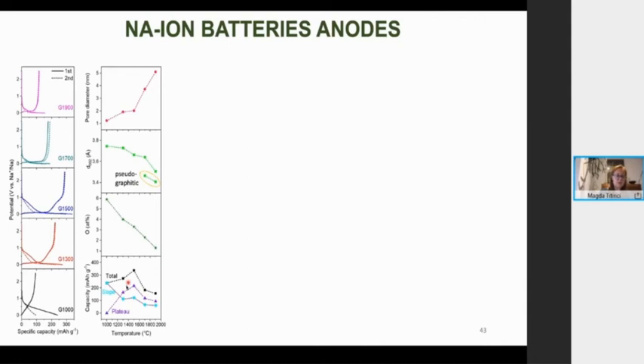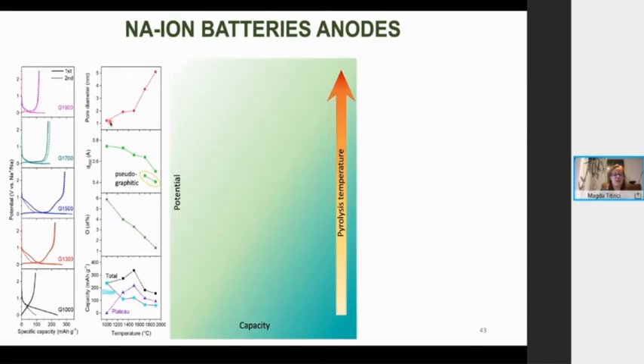And it seems there is a sweet spot where basically you have the right oxygen atoms because you do need some defects for sodium to absorb, dissolve, and this seems to be around here, around 3.5%. You want the right interlayer spacing, and the interlayer spacing should be just a bit more than 3.6 angstroms. And you also want the right pore size distribution, but more than this, for the pore size in sodium-ion batteries, you want the right amount of pores that are closed, but you also want your connectivity to those pores to be good, which we determine using pair distribution function and solid state NMR.